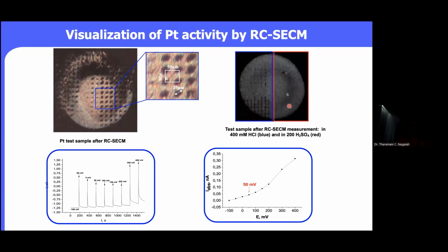To further confirm, we have done some chronoamperometric experiments. That means we are polarizing the sample and trying to monitor on the tip at various potentials at a particular time interval. And we have calculated the absolute current with respect to the potential. We can see that the chlorine starts to evolve at 50 millivolts itself, whereas we have applied almost 400 millivolts as a base potential, and the measuring potential is 150 millivolts. So that means we are already producing chlorine.